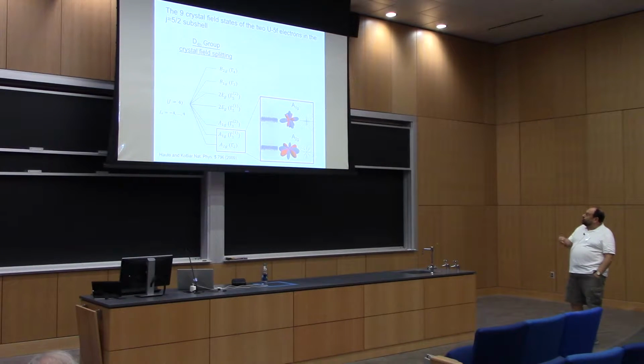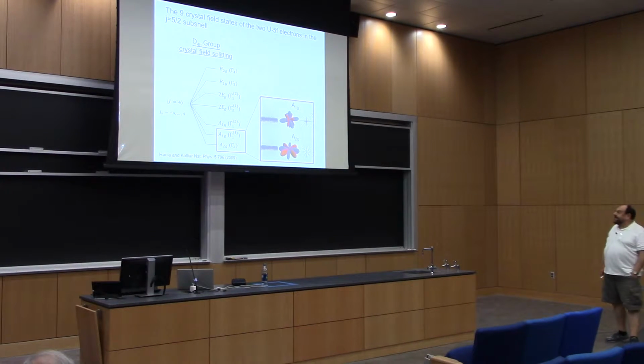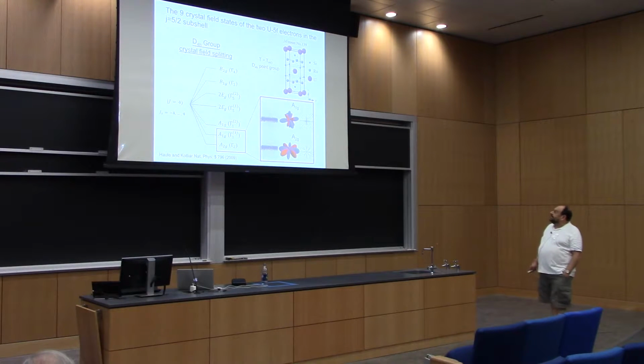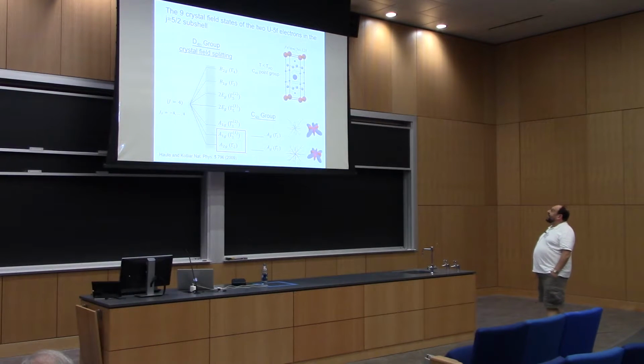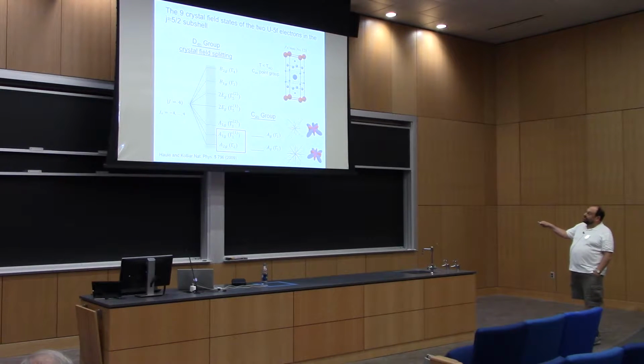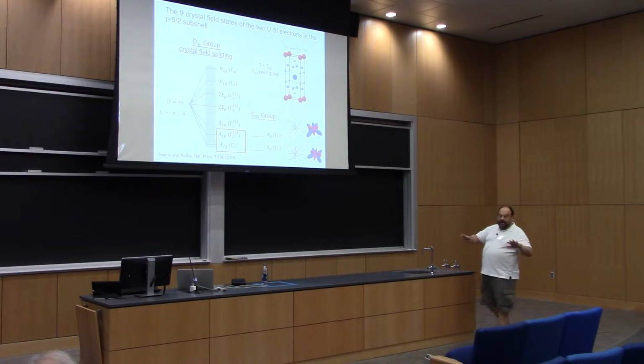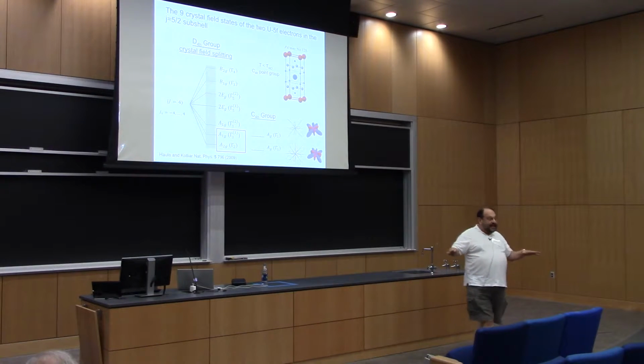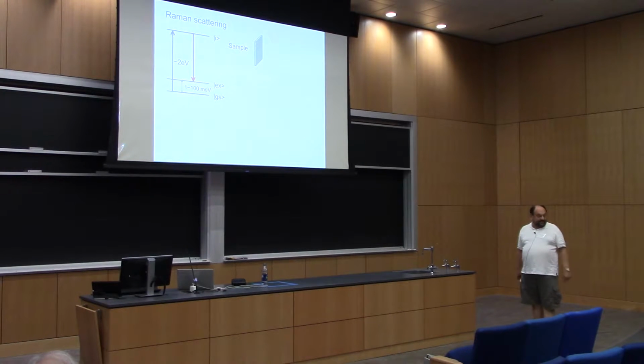study that Sean presented was that these two states, or other two states, connected by A2G matrix elements have to be mixed, and that the D4H group has to be reduced below the hidden order transition to C4H group. An absolute consequence of that is that there's going to be chiral symmetry broken, and then we can build a state which would be a chiral density based state, which will be consistent with hidden order.